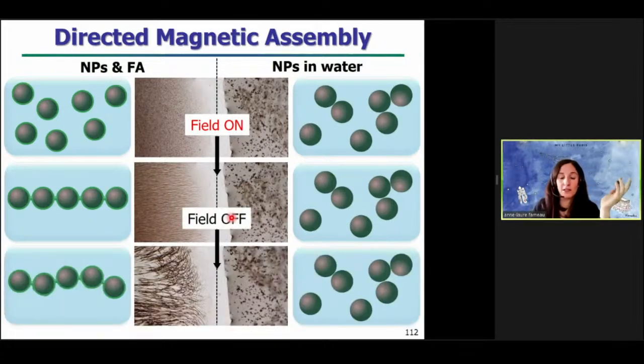We turn off the magnetic field. The filament structure persists for nanoparticles with fatty acid, and nothing happened for nanoparticles in water. So this simple experiment shows that it's really the presence of these fatty acids surrounding the nanoparticles that binds the nanoparticles together permanently, and that's why you still have the filaments after switching off the magnetic field.